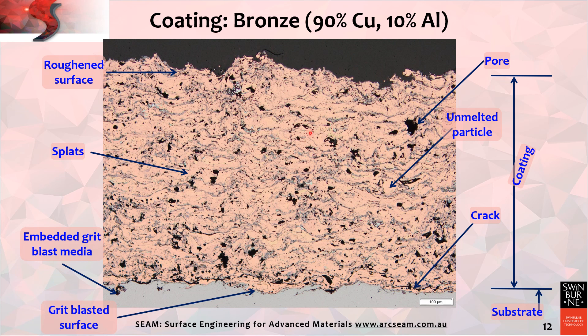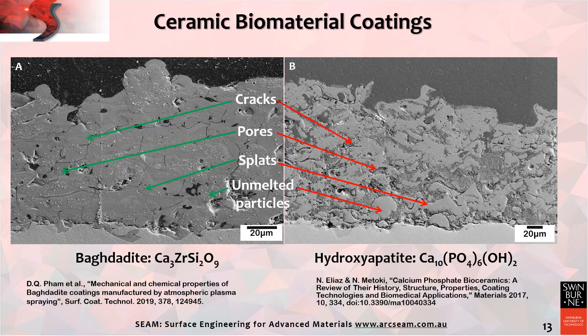This bronze coating illustrates some of these artefacts, which are typical for the majority of thermal spray coatings manufactured by two-wire arc, plasma, flame spray, as well as HVOF processors. Some thermal spray processors also typically produce dense coatings where the microstructure is more like the bulk coating. However, the additional feature is that of residual stress effects. Coating structures are complex.